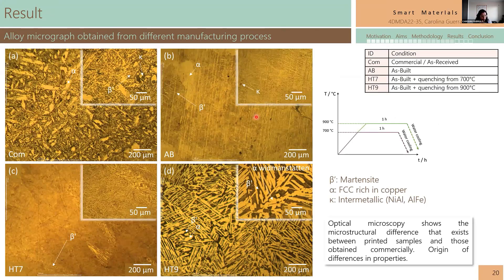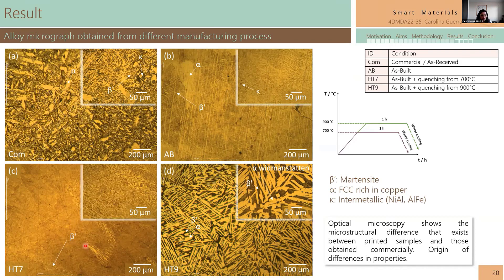After that, I chose the best laser parameters and compared the mechanical properties with the commercial sample, the as-built sample, and samples quenched from 700 and 900 degrees Celsius. The microstructure looks very different after heat treatment. When heat treated at 900 degrees Celsius, Widmanstätten-shaped alpha appears in the lighter zones, while the darker zones are the beta phase (martensite). At 700 degrees Celsius, the microstructures are finer than at 900 degrees Celsius — similar phases but different distribution.